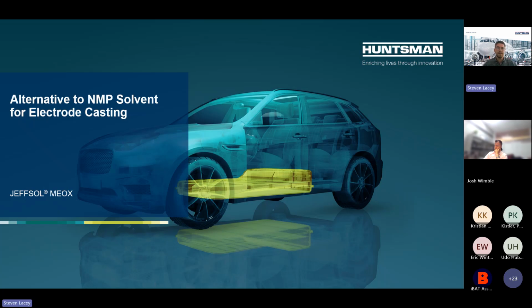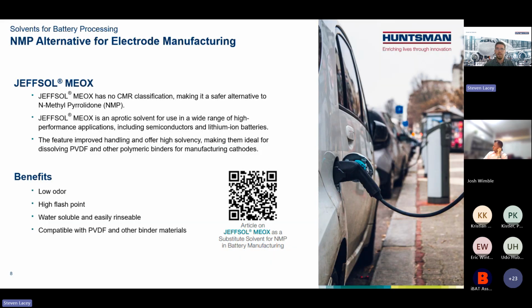So the first product I'd like to highlight is MEOX, which is the NMP solvent alternative for electrode casting. As we all know, NMP is very carcinogenic and toxic. So also different classifications in Europe and globally are making it less easy to use and also people are not willing to handle it. So here at Huntsman, we've created a new alternative solvent that has no CMR classification at all. It's a polar aprotic solvent, and it's used especially in the semiconductor industry and also for battery electrode manufacturing. In this case, we also have improved handling of this material, and PVDF and other binders can be readily dissolved into this to enable manufacturing of different electrodes.